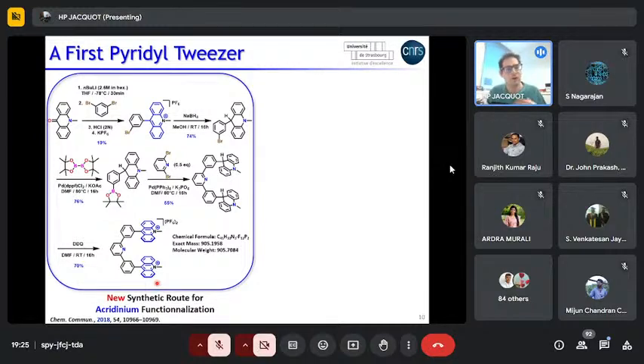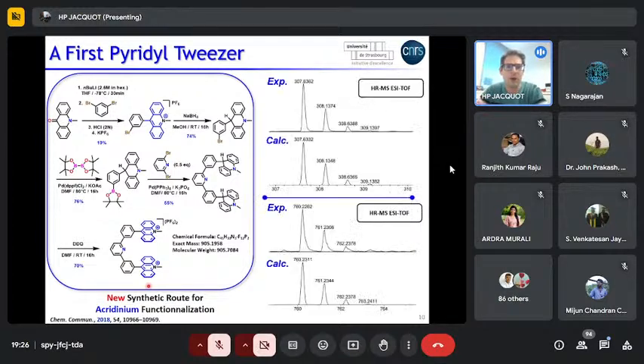The synthesis of this molecule is slightly different from what it was before. Actually, what we had to do was to form the acridinium core, but it has a positive charge and sometimes it leads to some tedious purifications. So we wanted to get rid of this positive charge. One way was to reduce the molecule into the corresponding hydroacridine. This molecule is slightly unstable under air since it slowly reoxidizes into the acridinium derivative, but still we can work with this, form the semi-rigid spacer, and finally, in the last step, we can oxidize using DDQ and get the molecule. The first evidence or proof of the existence of this molecule was provided by mass spectrometry.